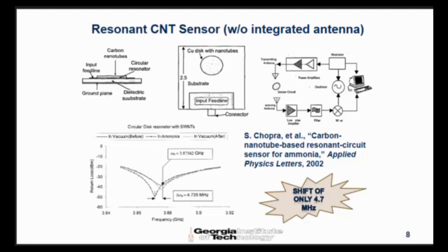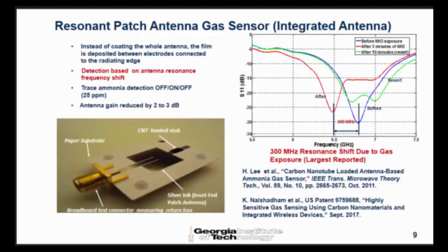And when the source of ammonia is removed, the sensor reverts back to the original condition, the equilibrium condition. So it's completely reversible. But the problem is that 4.7 megahertz on a grounded plane patch resonator can be very easily detuned by, for example, if I place the resonator on this desk, I can move the frequency. So in practice, this is not useful. So what we did at Georgia Tech is instead of coating the complete antenna with carbon nanotubes, we created a short stub extension. And in the stub, you have a small gap. And across that gap, we put this thin film of carbon nanotubes, which are specific to ammonia. And we repeated the same experiment which the previous authors did. And what we found is that there is a 300 megahertz shift, not 4.7, but 300 megahertz shift. Now we can manage this shift along with amplitude discrimination and so on, and we can get a very robust way of detecting gases using this resonant frequency shift.